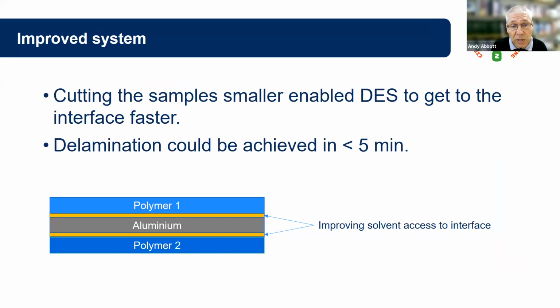Because as you make it smaller, rather than having to penetrate from the top and the bottom down to the interface with the metal layers, the solvent can work from the side in and penetrate that way, making it much easier and much faster. It still depends upon the types of polymers we've got, but our best separation time goes down to around 5 minutes.